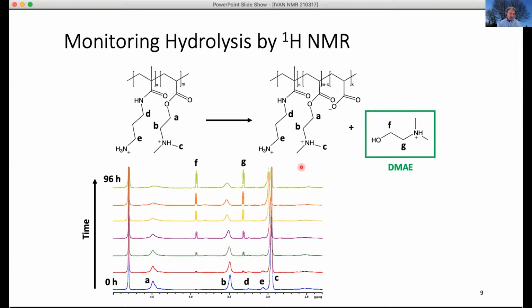We've done it in gels as well. In addition to the broad peaks of the polymer that disappear, you can see the appearance of F and G, two peaks that come from this DMAE, dimethylaminoethanol.